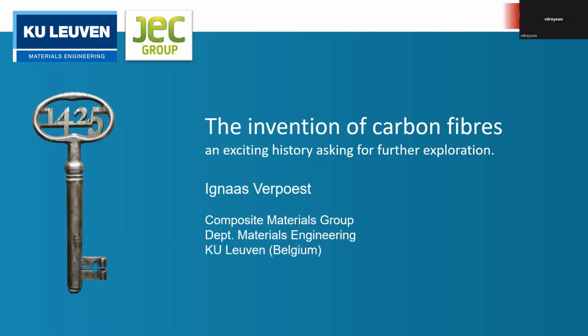I'm afraid that is one of the main problems for the lignin fibers. And the fact that already for more than 10 years people have been trying to make good lignin fibers might be related to that fundamental problem. Other people are mentioning the problem of the purity of the lignin material. If it's not perfectly pure, then you will have defects in the carbon fiber, which will lead to a lower strength compared to when you use polyacrylonitrile, which can be made extremely clean, extremely pure. And that is one of the strengths of companies like Toray and others who have the polyacrylonitrile production in-house. So they know that the polyacrylonitrile for carbon fibers has to be much cleaner and much more defect-free than the PAN fibers which are used for clothing or normal textiles. So that might be a second reason.